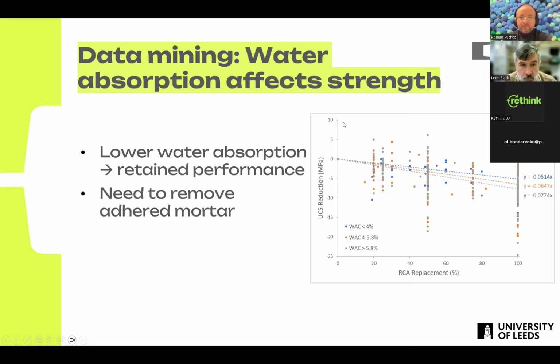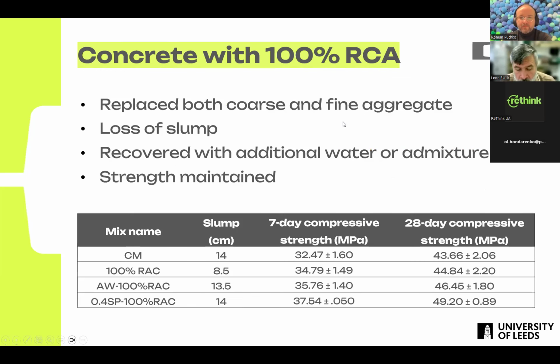So we then said, we've got this recycled aggregate. Instead of the modelling, we're now looking back in the lab and saying, how does this material behave when you put it in concrete? So we made concrete with 100% recycled aggregate. We replaced all of the sand, we replaced all of the natural aggregates, and just used recycled and processed coarse and fine aggregate.